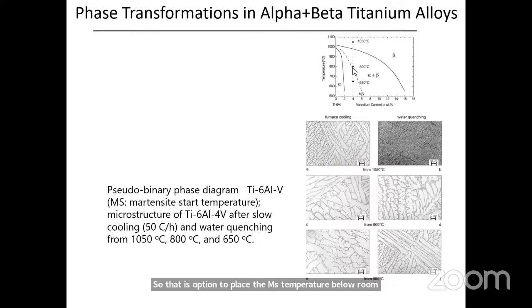So that is sufficient to place the MS temperature below room temperature. So when you heat the alloy at 800 degrees and quench it, you will not get martensite. You will get martensite only if you heat above 800 degrees centigrade and quench it. But at 800 degrees centigrade, the vanadium content of the beta phase is approximately 14%. That is sufficient to place the MS temperature, the martensite starting temperature, below room temperature. That's why even if you quench from 800 degrees centigrade, you will not get martensite.